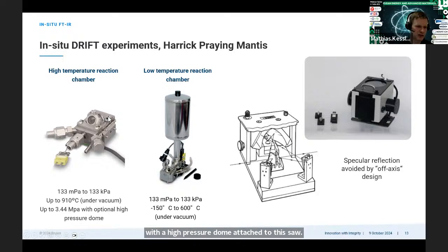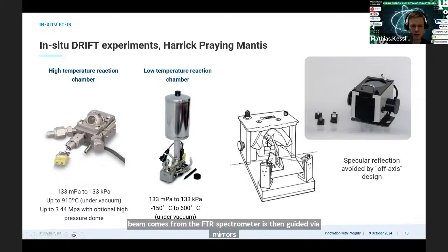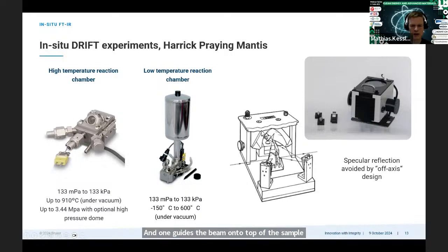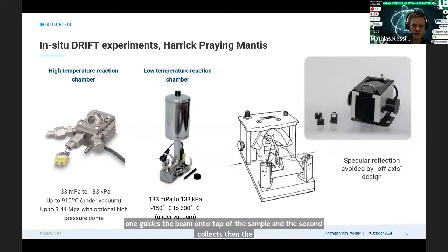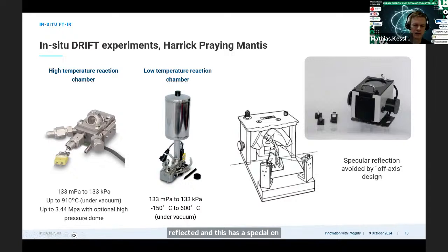So these cells have 3 windows. 2 are used for the infrared beam, which comes in and goes out here. And then 1 is available for observation, or if you want to shine, for example, UV light onto the sample to induce reactions. And here on the right side, you see the optical parts of the Praying Mantis cell. The beam comes from the FTIR spectrometer, is then guided via mirrors to the spherical mirrors here, and one guides the beam onto the top of the sample, and the second collects then the part of the light which is diffusely reflected. And this has a special off-axis design, and this avoids that we investigate parts of the IR light which are reflected specularly from the sample. So we collect only the part of the light which is diffusely reflected.